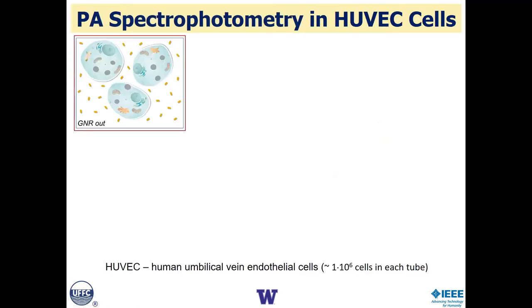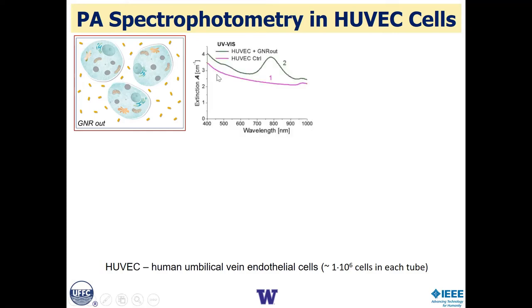What can you do with it? Well, let's go back to this example of nanoparticle trafficking in cells. We're looking at a specific case of HUVEC cells. These are endothelial cells that come from the human umbilical vein. We pick these cells because they can rapidly endocytose a wide class of nanoparticles. So this is just an example system. We then bring in the nanoparticles, in this case, simple gold nanorods, and look at the optical spectra that we can measure. So first we do this when we just introduce the nanoparticles into solution.